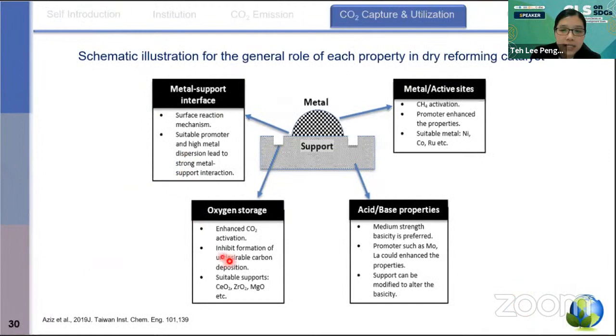So, we have this scheme from our group. We published papers on this DRM, and we propose that the DRM catalyst is composed of two parts. We must have metals and have a support. Then for the metal, usually it will be added as an active site for methane activation, because for DRM, we will react CO2 with methane. So it will act as methane activation. Then this metal can be used with a promoter to enhance the properties. Usually people are using nickel, cobalt, and also ruthenium.